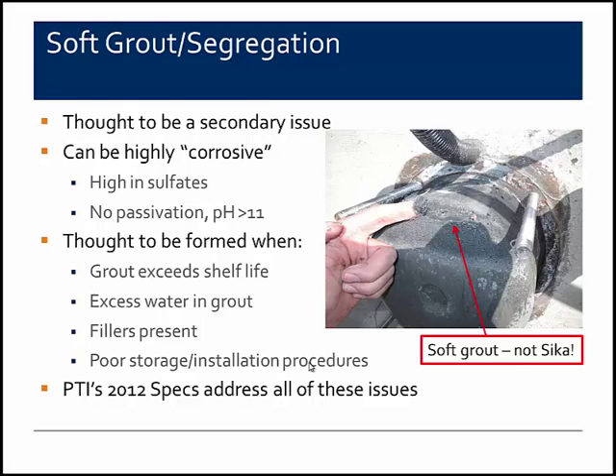What we have learned so far is that the soft grout can be highly corrosive, and I put "corrosive" in quotes because it's not the traditional corrosion that you might normally associate with chlorides. This soft grout, as that spectral analysis I showed earlier, is very high in sulfates, and apparently when you get a high sulfate concentration, it actually prevents the normal passivation of the steel that would occur due to the high pH of the cementitious material.